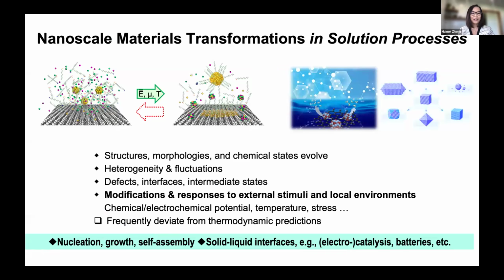Solution synthesis of materials, including many types of syntheses. During the synthesis and reactions, structure, morphology, and chemical state of materials evolve in response to the chemical potential, external stimuli, and the nanoscale local environment. Nanomaterials transformations are intrinsically complex, and they often exhibit heterogeneity and fluctuations where defects, interfaces, and intermediate states can strongly influence the transformation pathways. As a result, nanoscale transformations frequently deviate from thermodynamic predictions. These dynamic processes and their underlying mechanisms are often hard to probe using conventional approaches.